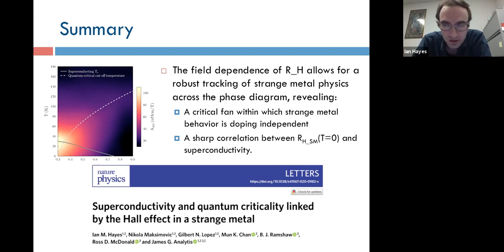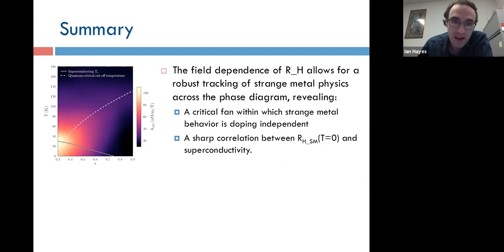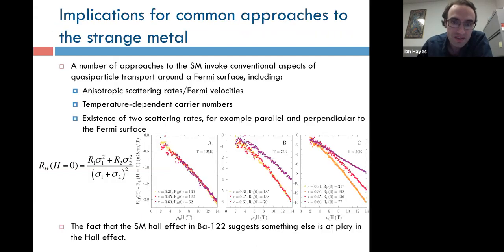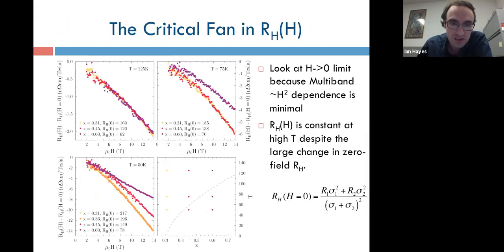I think generically you do expect whatever increase in RH you get from anisotropic scattering to decrease with field. So that way it is actually consistent. What I would like to see, and haven't seen because I'm sure it's difficult in a system like this, is whether you can actually reproduce a consistent field dependence at high temperatures despite all these changing background conditions. It's probably not impossible. The question is whether you're just going to be tuning parameters at the end to make